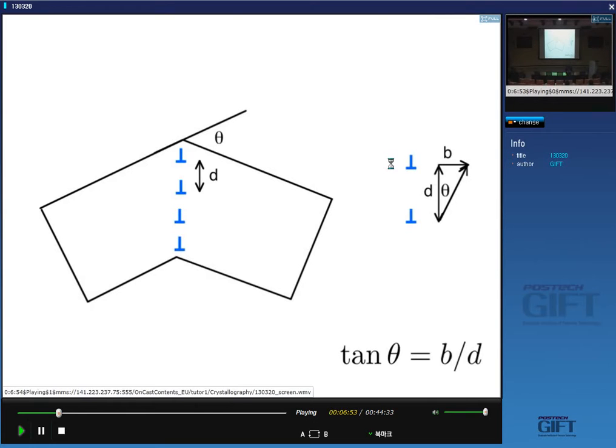Okay? So we have a dislocation model of the grain boundary, which is beautiful because we can see the dislocations inside the transmission electron microscope. We know they have Burgers vectors, and the spacing of the dislocations and the Burgers vector will be precisely related to the tilt angle between the two crystals. Okay? So very simple model, beautiful model. So we now go on from this model to work out the energy per unit area of the boundary.